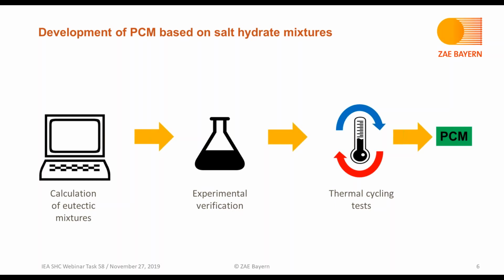After the calculation, the predicted eutectic composition needs to be experimentally verified. If this verification is successful, we are performing thermal cycling tests to test the material under application conditions. And if these tests are also successful, then we have successfully developed a new PCM.